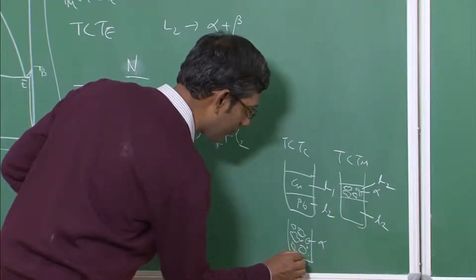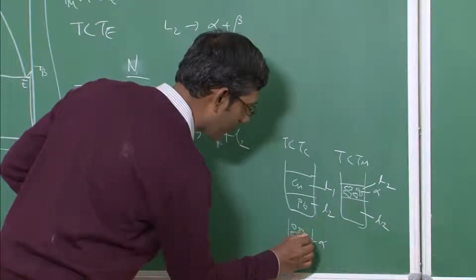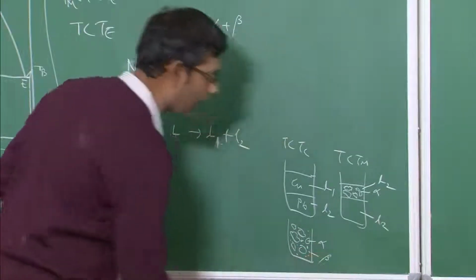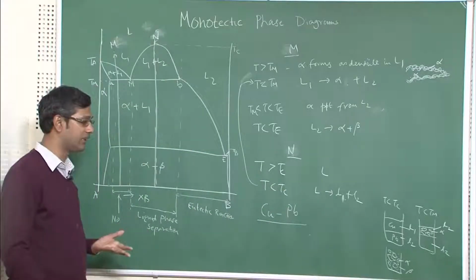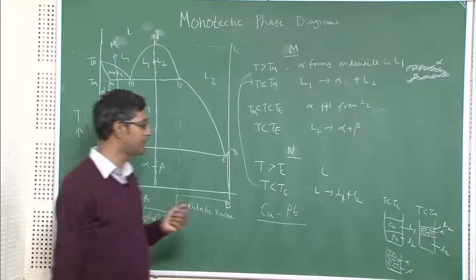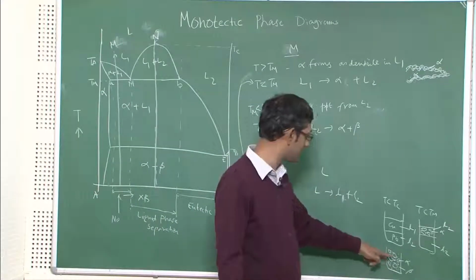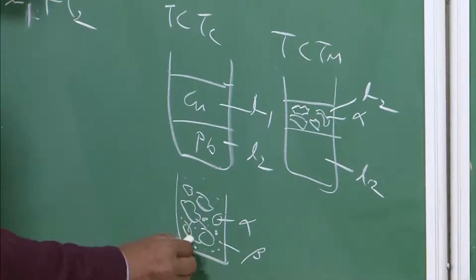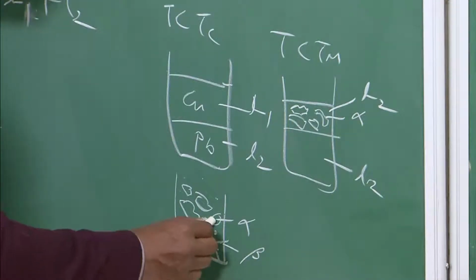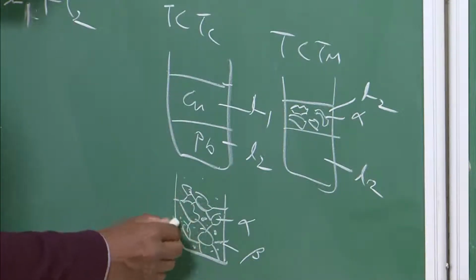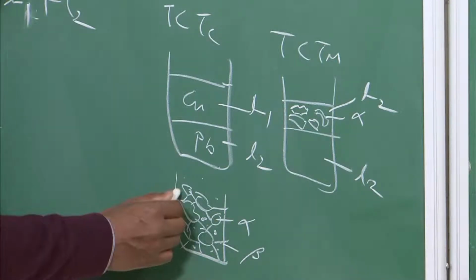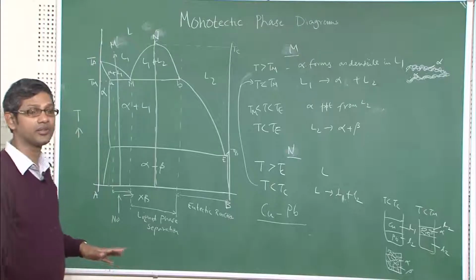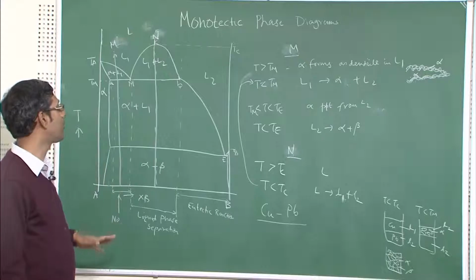and beta droplets in the microstructure will form, because the eutectic reaction will lead to a very small amount of alpha and a large amount of beta. Therefore, you will not see it, and that is what you see in the microstructure. Looking at the microstructure of copper-lead, what are you seeing? These are the large copper grains, and within that you have beta or lead droplets present, correct. These are the lead droplets I have drawn here, and that is exactly what will happen in a real microstructure. Exactly this is what will happen.